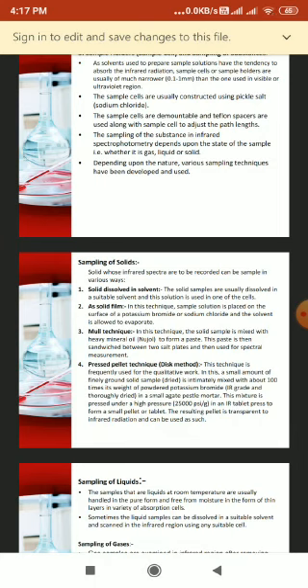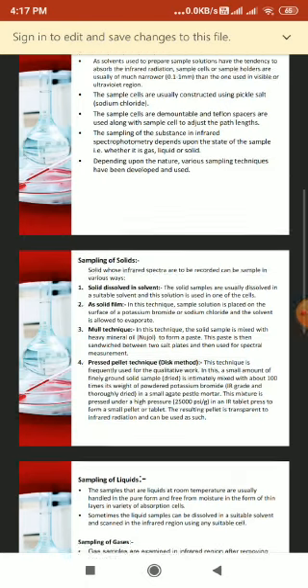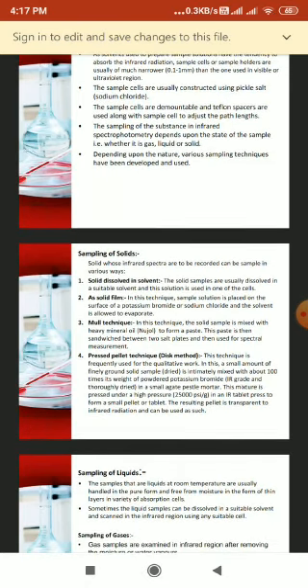Fourth way is the pressed pellet technique. It is also called the disc method. This technique is frequently used for qualitative work. In this, a small amount of finely ground solid sample in dried form is intimately mixed with about 100 times its weight of powdered potassium bromide in a small agate pestle and mortar. This mixture is pressed under high pressure, meaning 25,000 psi, in an IR tablet press to form a small pellet or tablet. The resulting pellet is transparent to infrared radiation and can be used as such.